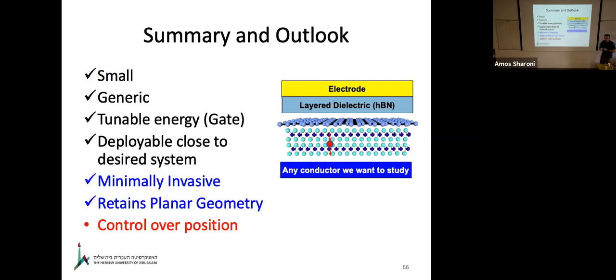I showed you that we have defects, and the defects are small because they're about an atomic state. They could be a bit larger because a defect state is not strictly atomic. It's a bit bigger than an atom. They're generic because they can put various kinds of conductors as long as they engage well with the barrier. The energy is tunable if I can use a graphene gate source through which I can gate the dot. I can deploy them very close to the desired system.